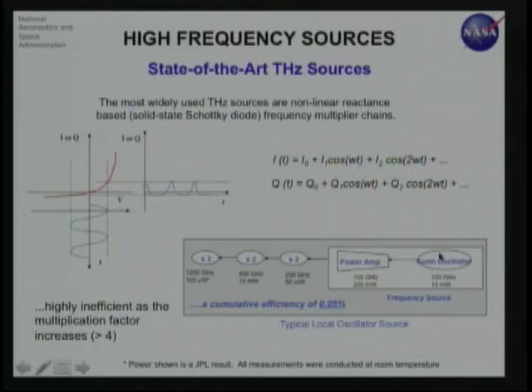For example, here's a typical 1.2 terahertz source. You start with a gun oscillator at about 100 gigahertz and about 10 milliwatts, which goes through a power amp that increases the power to 250 milliwatts, then through two doublers and a tripler to reach 1200 gigahertz. But notice what happens to the power: it drops to 100 microwatts. So when you do multiple stages, your cumulative efficiency is about 0.05%, which is pretty bad.